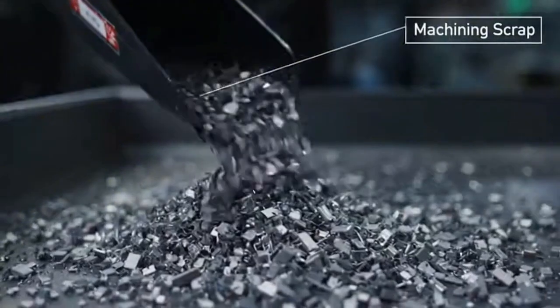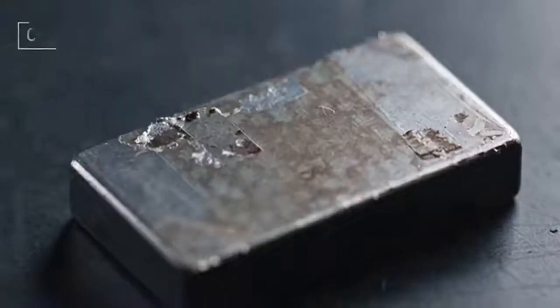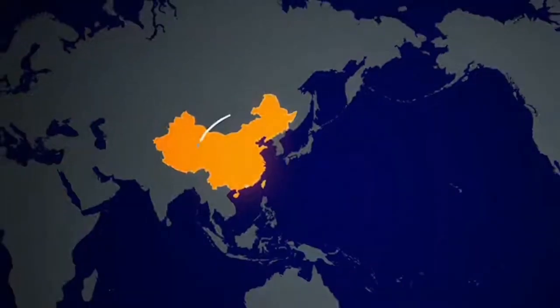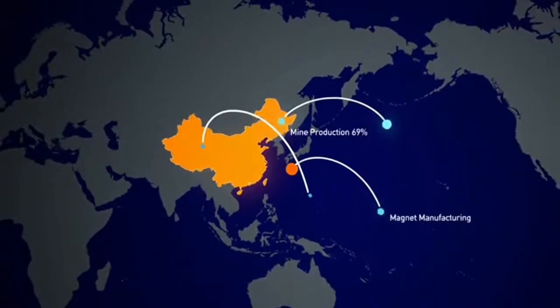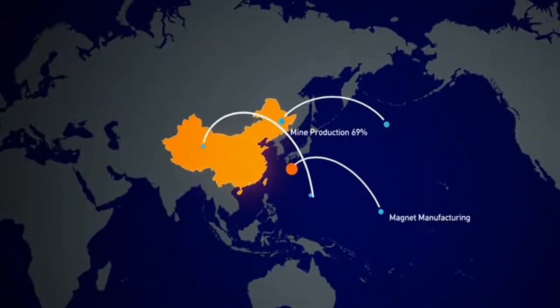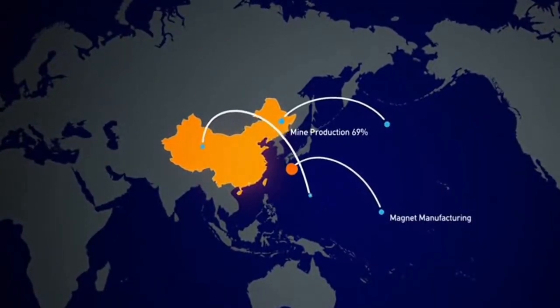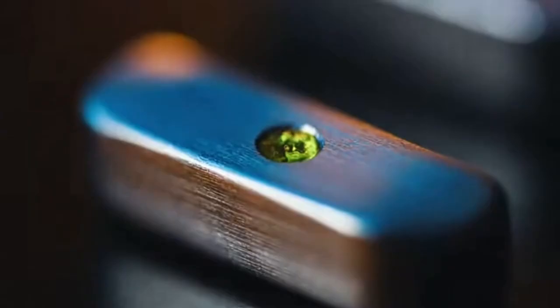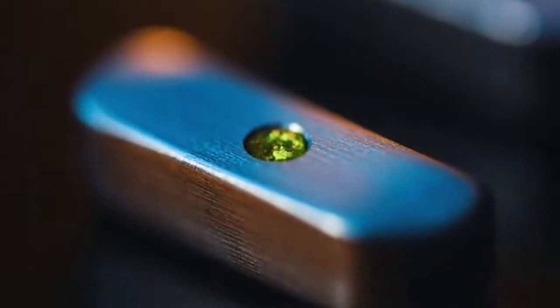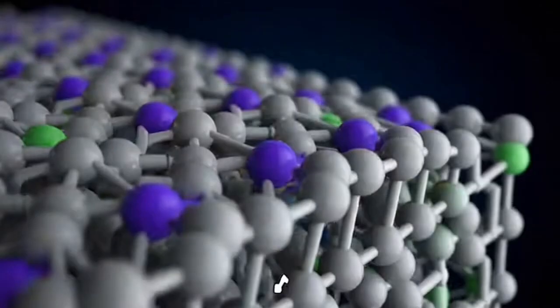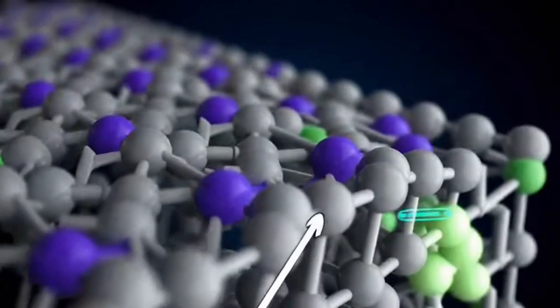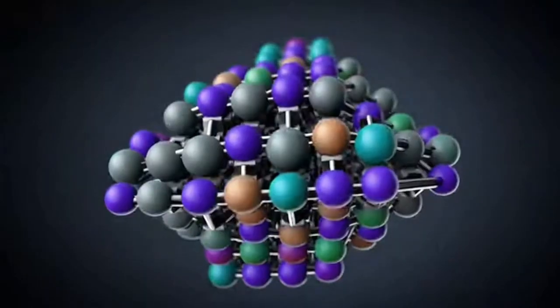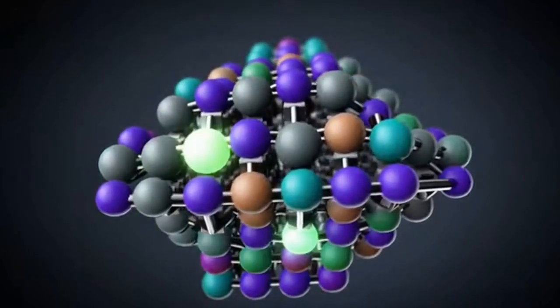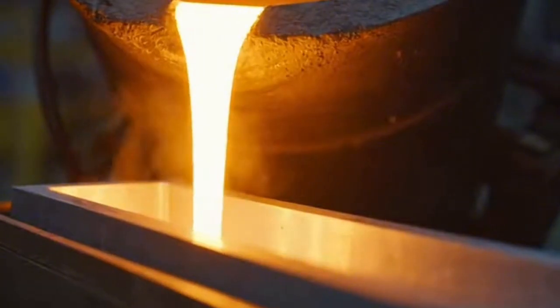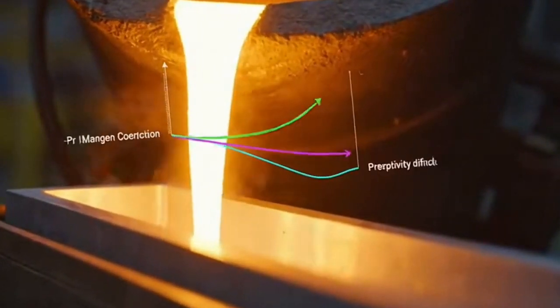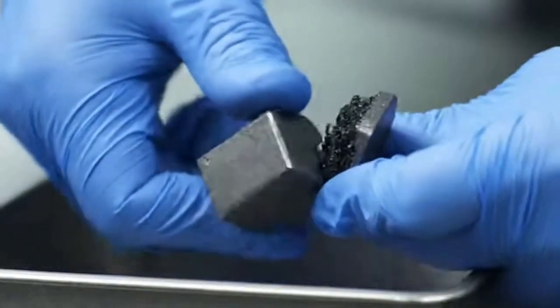To get to alloy, you must make metal, or at least a metal-bearing feed that behaves like one inside an induction furnace. The orthodox route for these lanthanides is to turn the oxide into a fluoride, then let electrochemistry do the heavy lifting in a molten salt bath. Hydrofluoric acid has a reputation that is well earned, so you treat it with the respect you give a wild animal, and you react your oxides to make rare earth fluorides that behave properly in electrolytic cells.